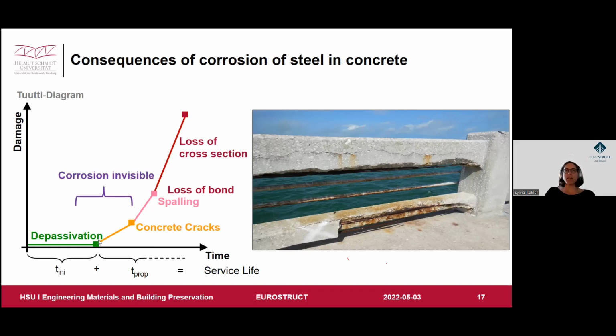And just from the point from depassivation to concrete cracking, here it's the most difficult point to guess in which condition our structure is, because corrosion is not visible. If we do not see any cracking, we have no chance to assess corrosion just from visual inspection. This is a critical point where you do not know, is my structure corroding or not?